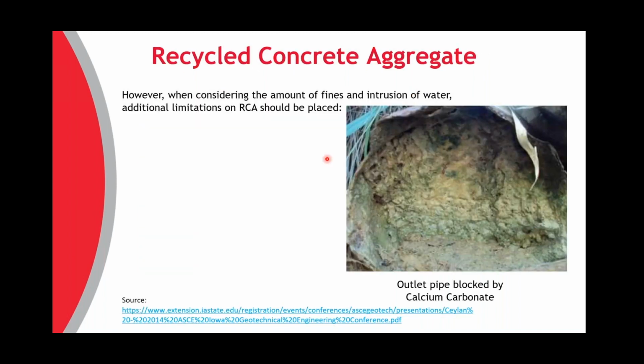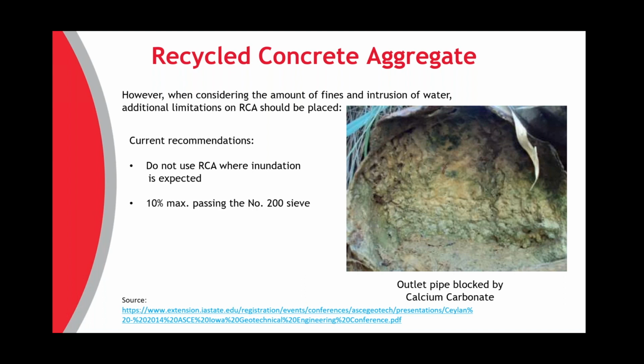However, with the RCA, there are some drawbacks. You'll notice this picture here is kind of hard to make out, but this is calcium carbonate that has blocked a drainage pipe. The fines in the crushed concrete aggregate and water can form calcium carbonate. So the current recommendation, if you use a recycled concrete, is to not use it where it's expected to be inundated, such as coastal areas where it's affected by tidal fluctuations. Limit the amount of fines to about 10%, and include drainage provisions to prevent water infiltration into that zone. So that's recycled concrete aggregate.